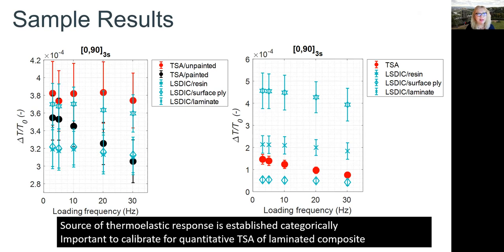More importantly, it allows you to determine what is happening at lower loading frequencies, because if you cycle composite materials at high loading frequencies, you risk viscoelastic behavior occurring. So this allows us now to be able to conduct thermoelastic stress analysis on complex components and be able to interpret results quantitatively. Thank you for listening to me.